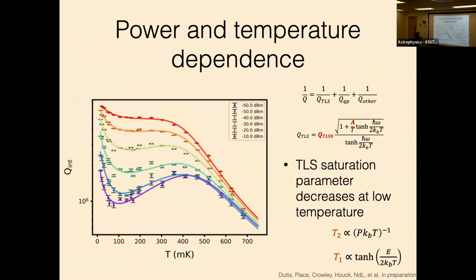Okay. So actually, specifically, if you look at this curve, I didn't really talk about it very much, but this part is just like partition functions, so that's obvious. But this part is weird, the fact that you get this really steep drop off. And it turns out that there are models that Phil Anderson wrote down in the 60s that just account for this. So if you just have TLS interactions that determine your line width, then there's a 1/T dependence to their T2. So at very low temperatures, you get extremely long coherence times for the TLSs, and then that makes their saturation power very, very low. So this saturation power actually corresponds to something like you need a 40th of a microwave photon to saturate all the TLSs in the resonator, which is kind of amazing.